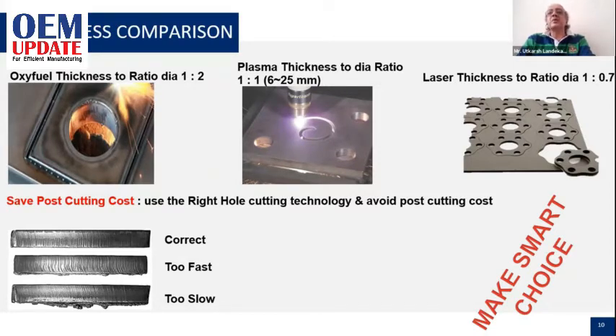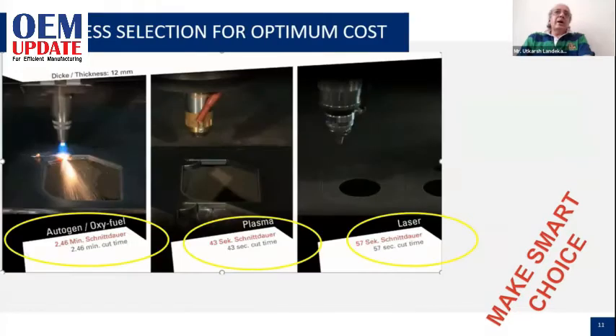Also, another important factor is the surface finish required. So we really need to make a smart choice between these three processes, whether it is really required to get into laser or there is another process which can substitute it. Time is limited in the industry, so what is the process that will be fastest? As per our standard calculation, when you want to cut a 12 millimeter plate, the fastest process is always plasma, and plasma has been scaled up to 600 amperes, which cuts very fast, and no process can match it.